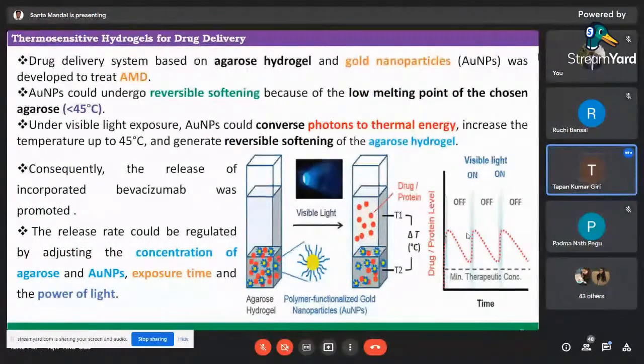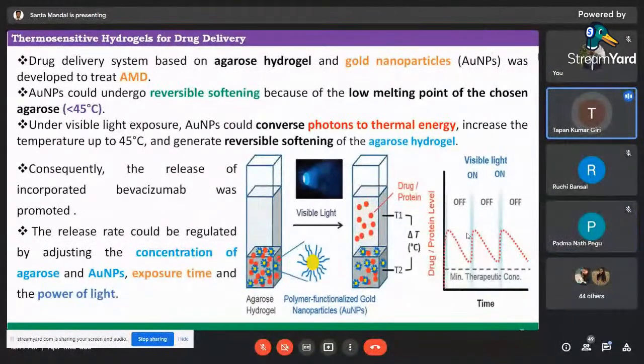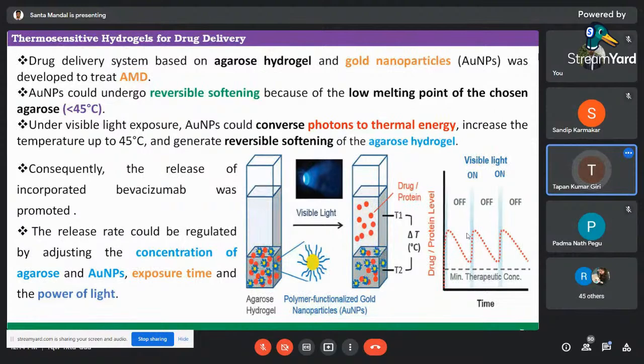So for AMD treatment, a drug delivery system based on agarose hydrogel incorporating gold nanoparticles was developed. The hydrogel could undergo reversible softening because of the low melting point of the chosen agar. The agarose hydrogel is thermosensitive, melting at less than 45 degrees centigrade. When we apply a light source, under visible light exposure, the gold nanoparticles present inside the agarose gel convert photons to thermal energy, increase the temperature up to 45 degrees centigrade, and generate reversible softening of the agarose hydrogel.